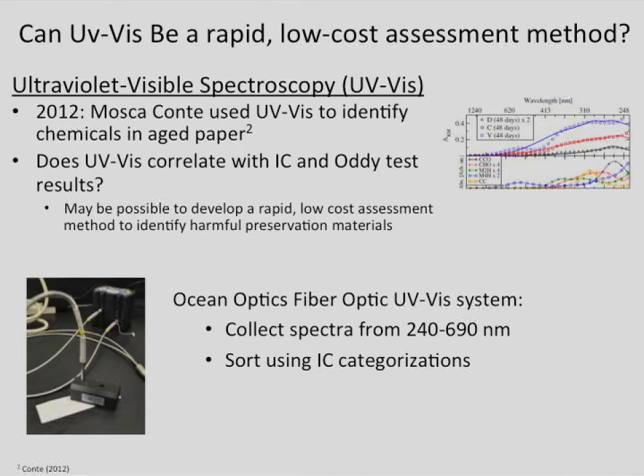Especially something simple like spectroscopy. I'm not the first person to mention this - other people have been trying to relate spectroscopy to the physical methods or measurements we're making, including gel permeation chromatography, pH, and so on. There is literature out there that suggests if you age paper in closed vessels - that's what this V is - you can increase the UV absorbance of that paper. This is a high cellulose content paper with no lignin that they were looking at. This is not my work, it's from the literature.